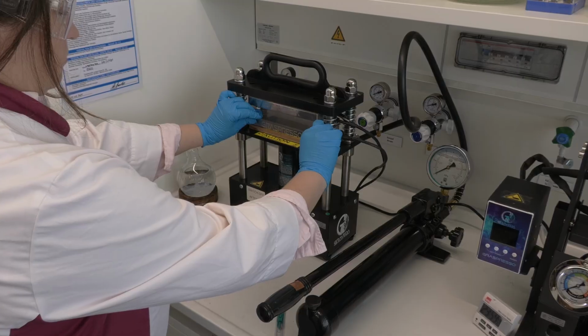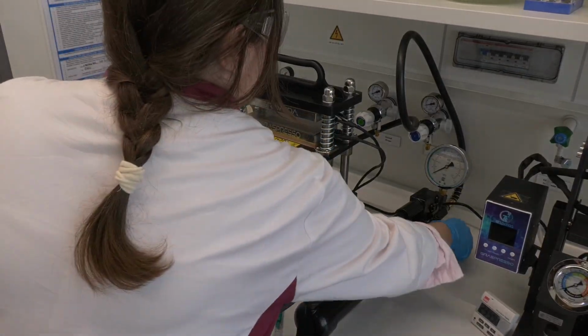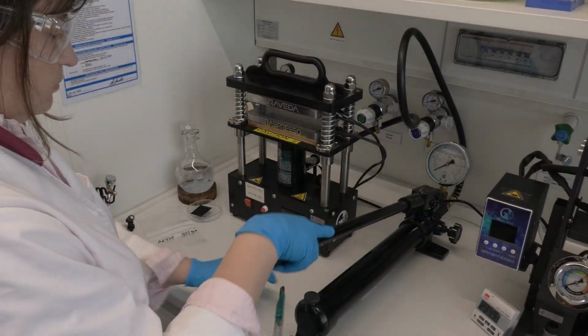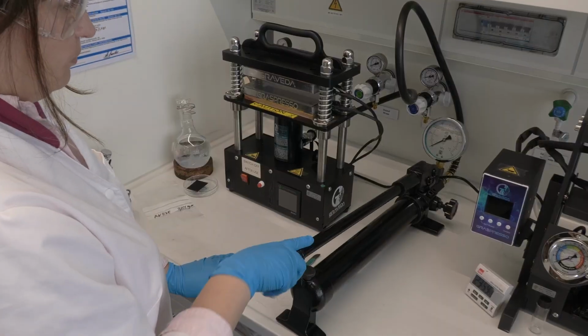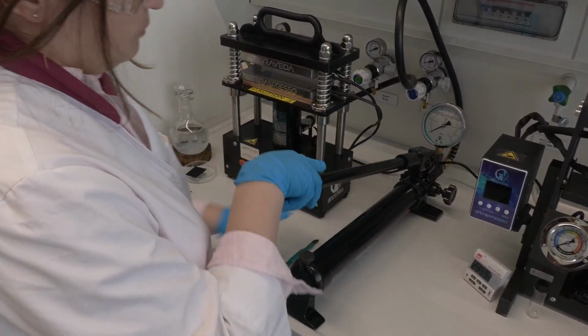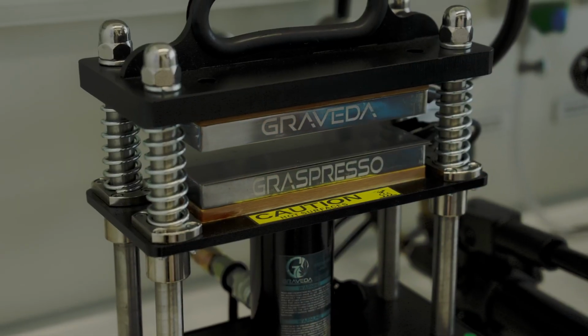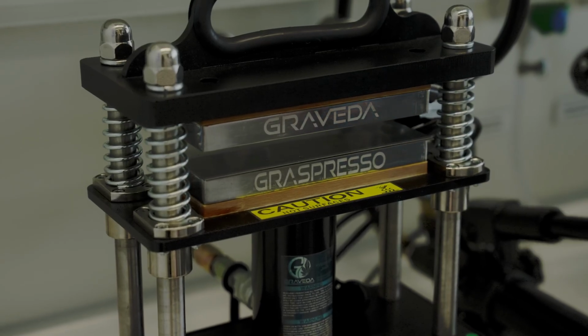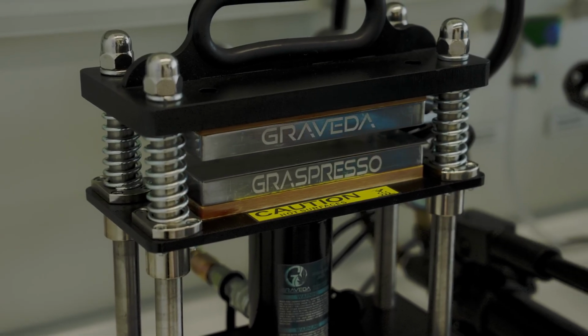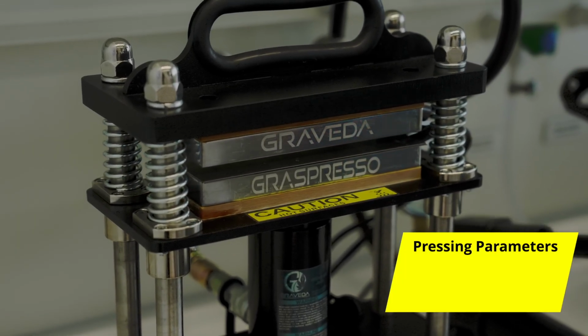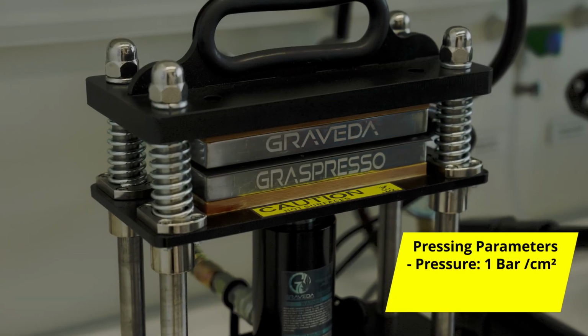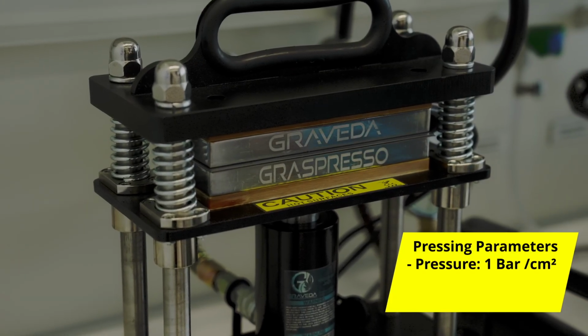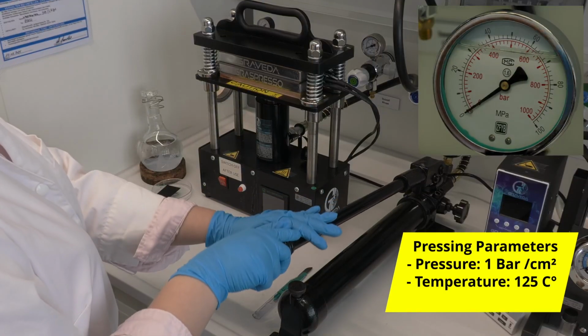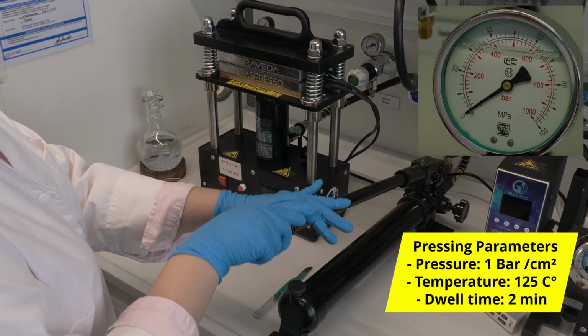We use an air-cooled press designed to press 2 samples, each measuring 2.2 by 2.2 centimeters. According to the cell design recommended by the manufacturer, we perform hot pressing under specific temperature, pressure, and time parameters. Parameters: pressure 1 bar per square centimeter, temperature 125 degrees Celsius, dwell time 2 minutes.